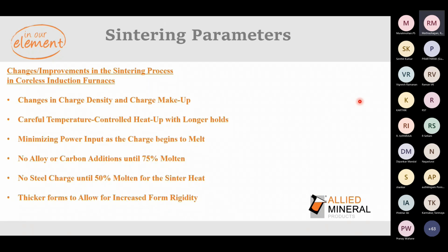So when it comes to sintering parameters, care has to be taken, and I'd like to talk about that here, which is changes in the charge density and charge makeup. Make sure the charge is dense, clean, oil-free, rust-free, no borings. Make sure you follow the right cycles with the holds wherever recommended. Like I said, for silica, 550 to 600 degrees Celsius or 900 to 1000 degrees Celsius, and then the final hold. Minimize the power input as the charge begins to melt. No alloy additions or carbon additions until 75% of the furnace is full. Don't add steel charge until 50% molten metal during the sintering heat, which we'll talk about later in the presentation.